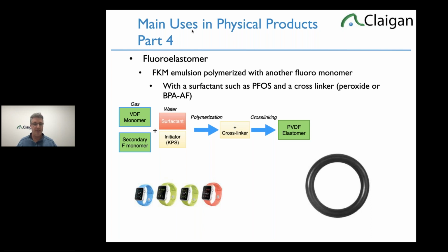It's basically a VDF. So it's of the PVDF family. It's a VDF monomer, a little bit, with a secondary fluoromonomer of some kind. It could be tetrafluoroethylene. And it comes in a gas, it's the oil side. You add water, you put in a surfactant like PFOS. So the surfactant is also why these PFOS and PFOA are used. They're to mix oil and water. Because inside the water is the thing that makes the monomers connect, bind and become a polymer, the potassium persulfate, KPS. That's the initiator. It causes the different monomers to bind to create longer chains, which is a polymer.